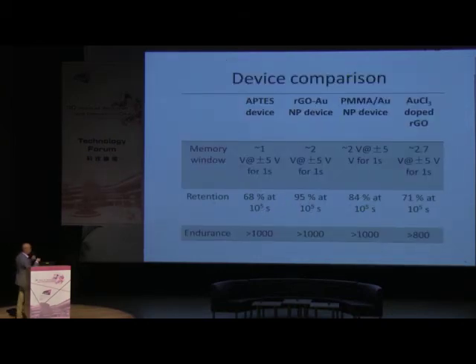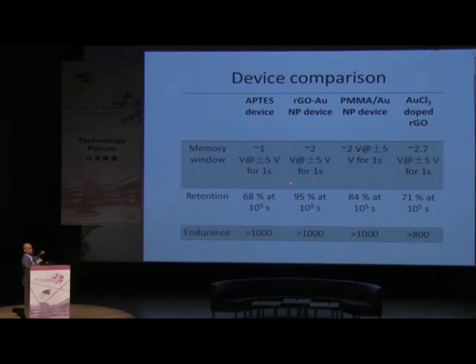At the end, if you compare all these devices, in fact, the layer by layer ones have a longer retention time. Like when you have a layer of metal nanoparticles and graphene on the top, because they have two barriers, the charge cannot easily escape. On the other hand, if you compare the memory window or the data storage capability, the doped graphene is much better. You can go up to 2.7 volts, which is much higher than these other devices. But if you see here, the retention time is much smaller.